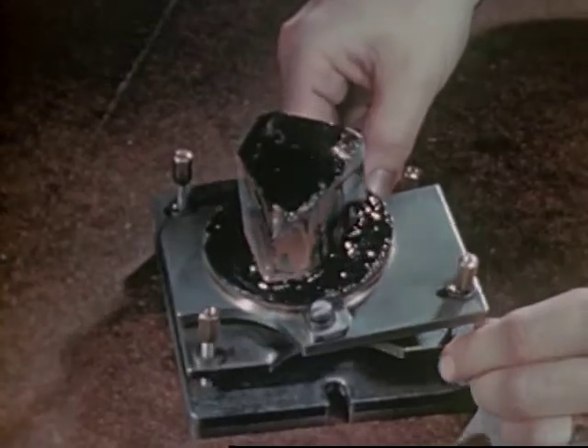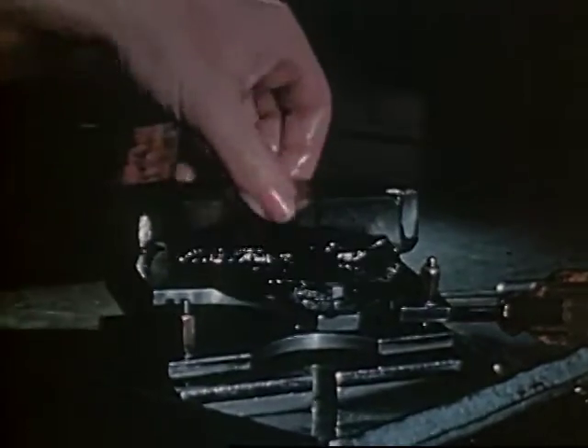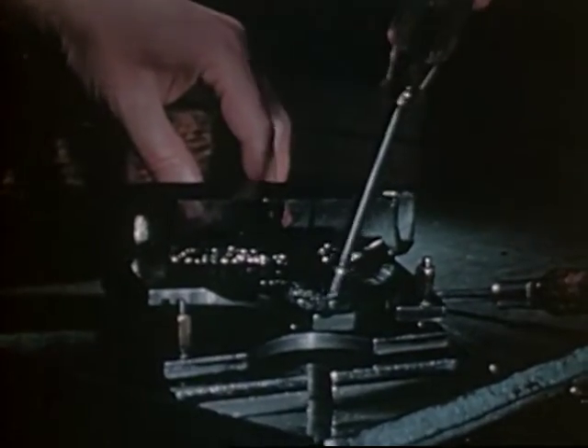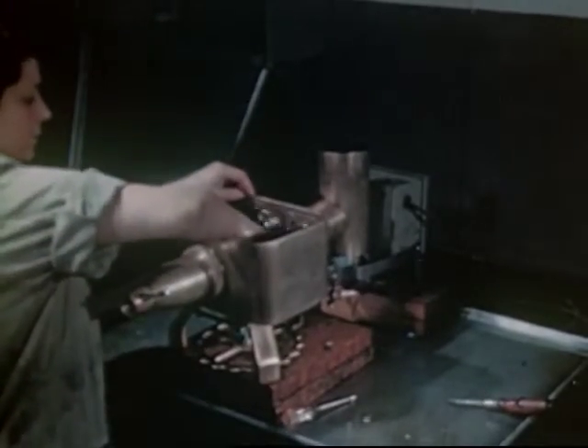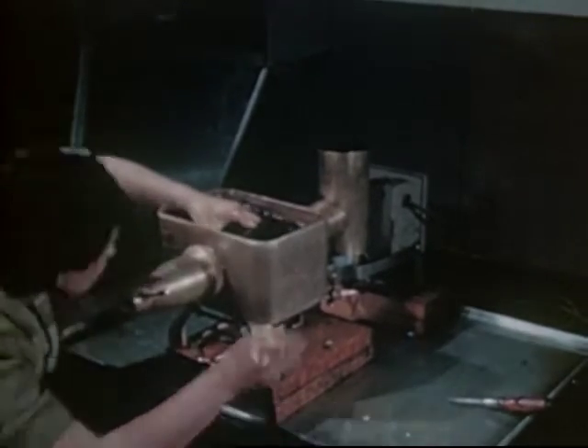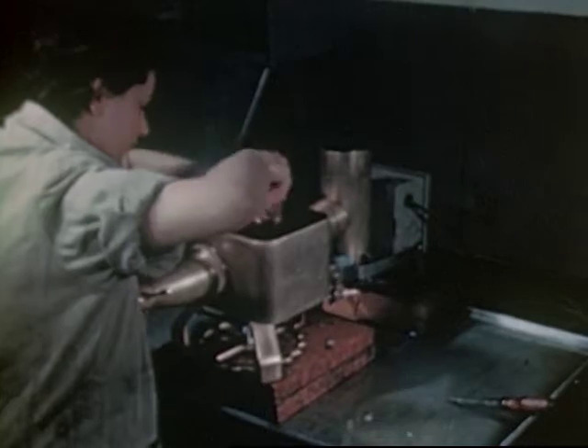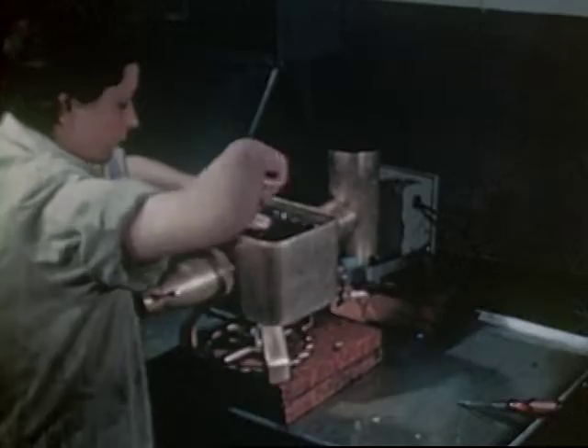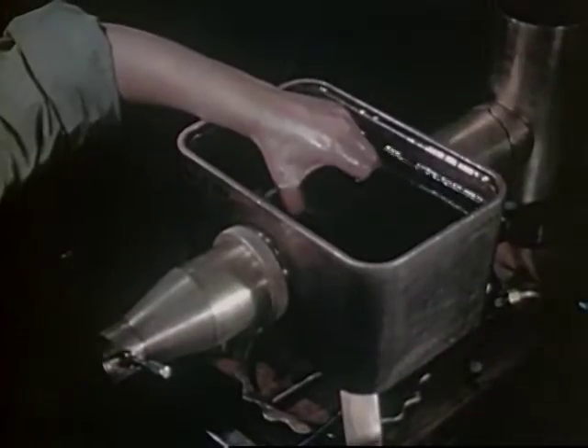The quartz, firmly bolted on the adjustable jig, is again submerged in the oil of the conoscope. The quartz is to be aligned in relation to the internal structure of the quartz rather than to the surfaces of the rough bar. With this flat bar, the optic axis shows itself as the center of a very perfect set of colored rings which appears in the eyepiece. These rings shift as the bar is turned ever so slightly. The task is to center the rings on the crosshairs of the eyepiece. When this is done, it determines the optic axis with good precision.